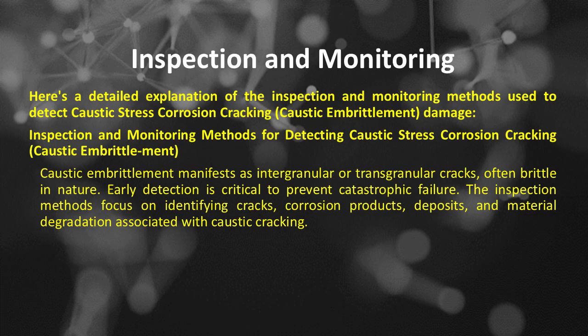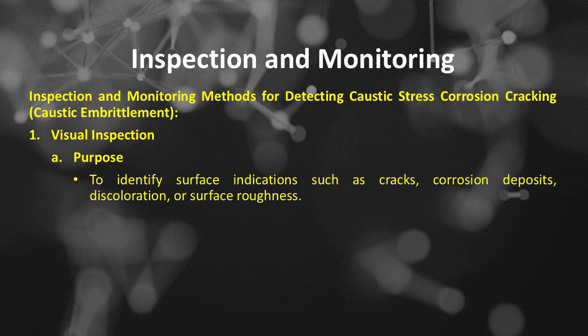damage. Caustic embrittlement manifests as intergranular or transgranular cracks, often brittle in nature. Early detection is critical to prevent catastrophic failure. The inspection methods focus on identifying cracks, corrosion products, deposits, and material degradation associated with caustic cracking. Here's a detailed overview of inspection and monitoring methods for detecting caustic stress corrosion cracking or caustic embrittlement.